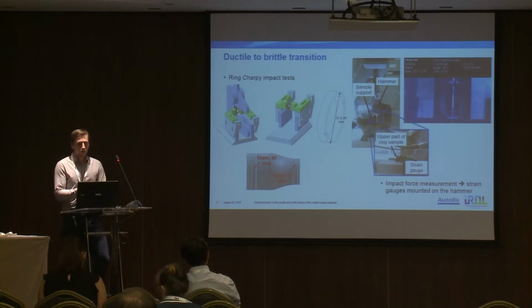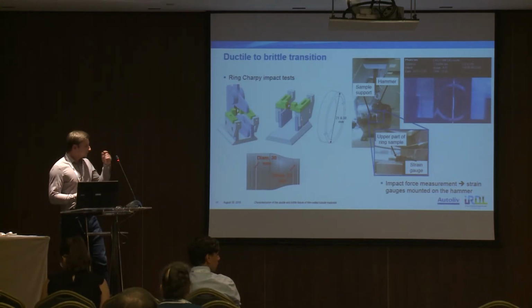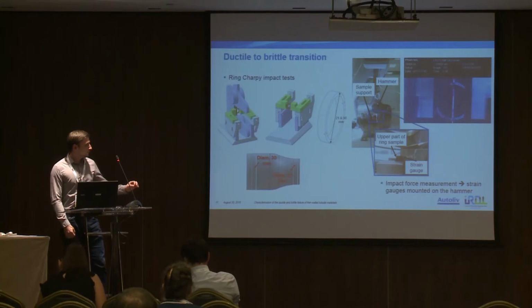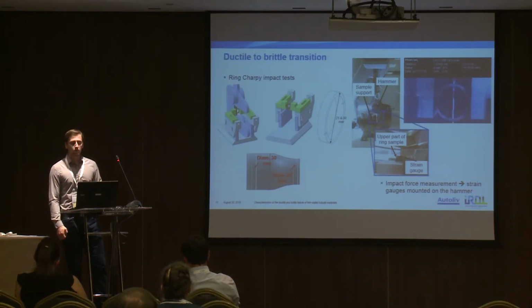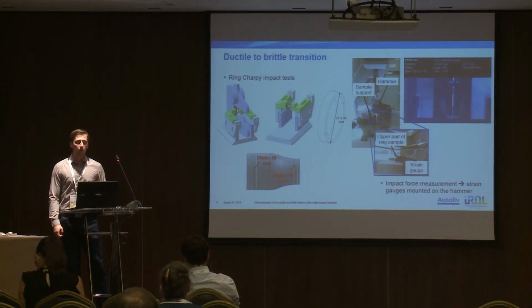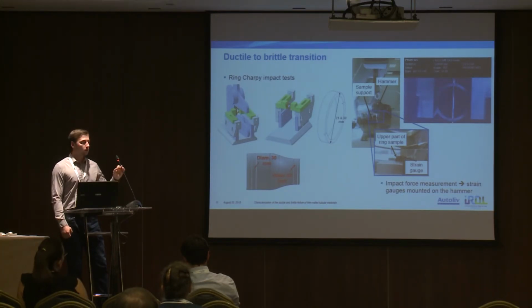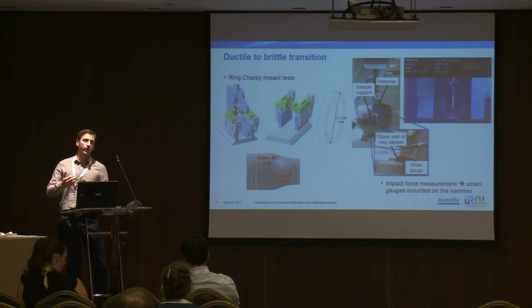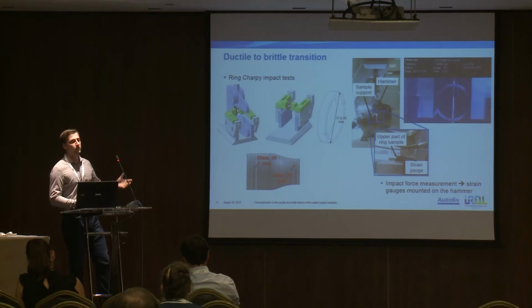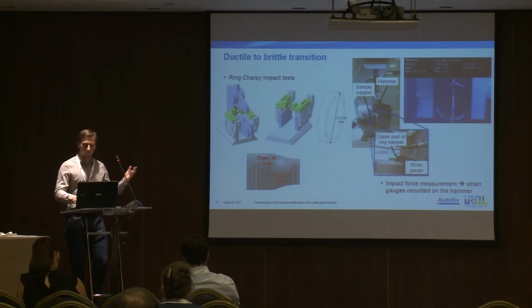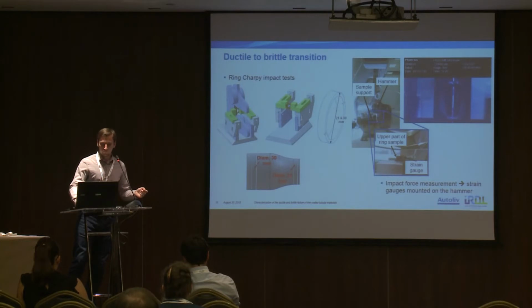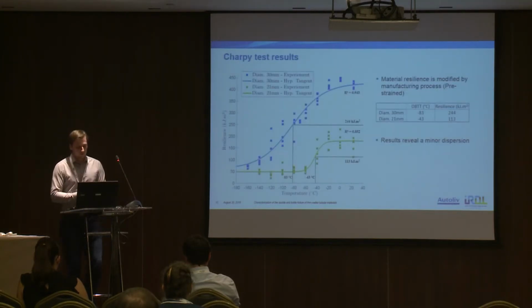So, also, we have a last really important point, because the impact force measurements were done not using a classical instrumented Charpy hammer, but with strain gauges mounted on the hammer in front of the sample. This gives quite good results, and if you want to discuss this method, I will answer you at the end, of course.